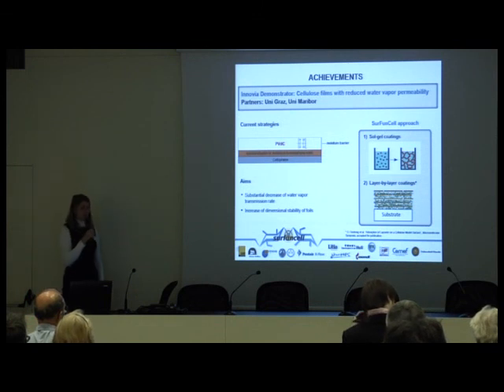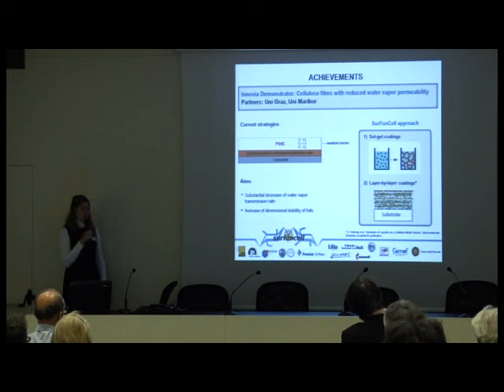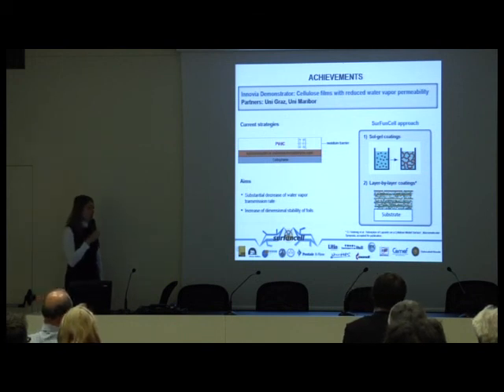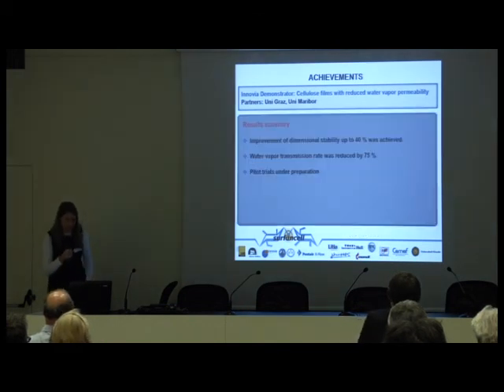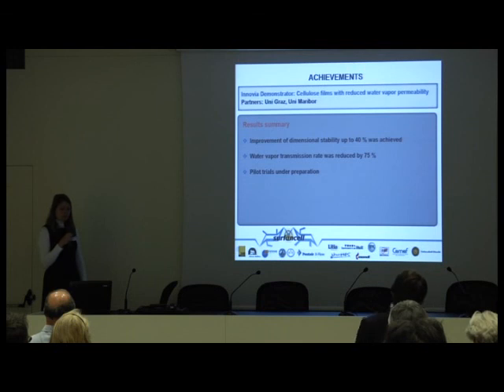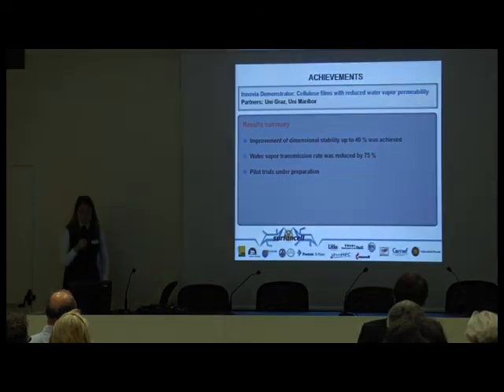The approach applied in SurFunCell is sol-gel coatings, as seen in the first picture, and layer-by-layer coatings containing polymers and platelet particles. The results achieved so far include an improvement of dimensional stability of up to 40%, a reduction in water vapor transmission rate by 75% compared to the original uncoated foil, and pilot trials are ongoing at the moment.